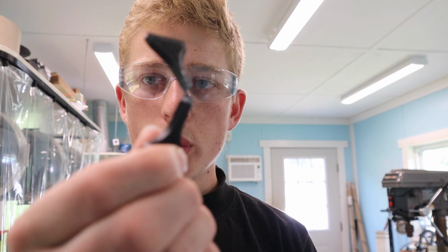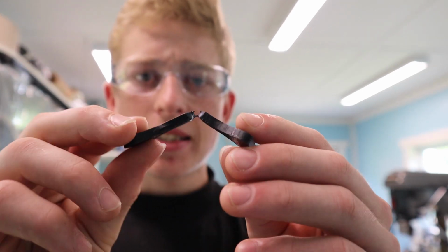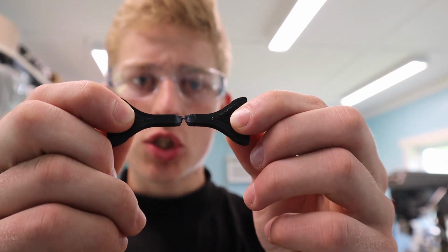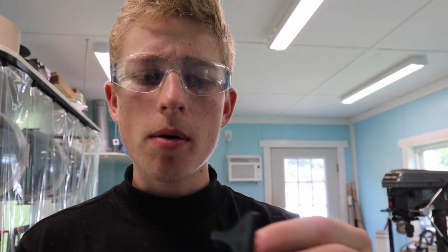All those samples broke around 260 pounds, 250 pounds. I still have to calculate the PSI, but it was kind of interesting because two of the samples, the two later ones, failed with a bit of plastic deformation, as you can see there, and it kind of stressed before, actually this one's still connected. The first one we did, on the other hand, just snapped apart and broke, which is kind of interesting.